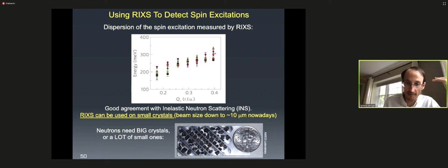So for example, here is an illustration of what it would take if you were to do that inelastic neutron scattering experiment. You would have a student spending weekends and nights, and of course weekdays as well, aligning all those different pieces of single crystals, because these are samples that you cannot grow big single crystals of. You can only make maybe a couple of millimeters, or even a couple hundred microns, of a sample, and you're going to need something big like this for neutrons. So you need all those individual crystals aligned perfectly with respect to one another to be illuminated, or excited, by the neutrons.